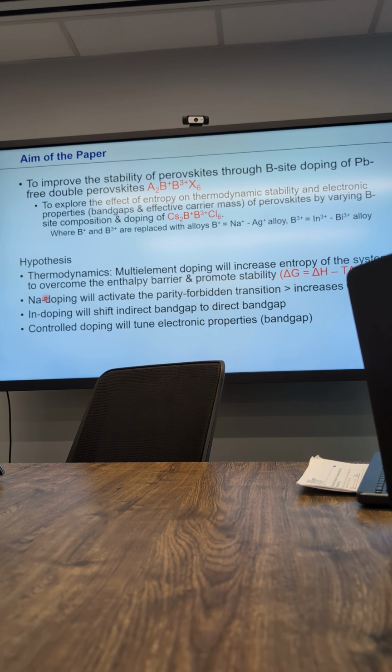Another thing they studied was their hypothesis was that sodium doping will activate that parity forbidden transition we talked about to increase the quantum efficiency, and indium doping will shift the indirect band gap to direct band gap. So one of the challenges.